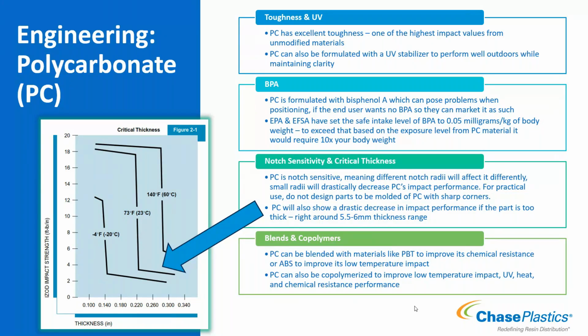BPA should be talked about because it is a part of polycarbonate and we get asked about it. BPA is part of the chemistry - we react phosgene and bisphenol A to make polycarbonate. So if you have an end user, or you are an end user, and you want to market that the material has no BPA, you're not able to do that with polycarbonate. Polycarbonate is made with BPA, it is there. The one thing I do want to point out is that based on safe harbor levels established by the EPA or the EFSA, the European safety standard, they have set a safe level at 0.05 milligrams per kilogram of body weight.